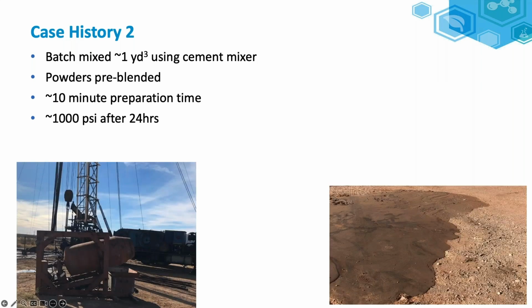There was enough success that work continued. System was changed a bit, so now everything was pre-blended in powdered form. The job was small. This was going to be the first job, a casing leak. He had his own cement mixer, so roughly a 1-yard cement mixer. Materials could be blended in the mixer and then pumped within about a 10-minute frame.